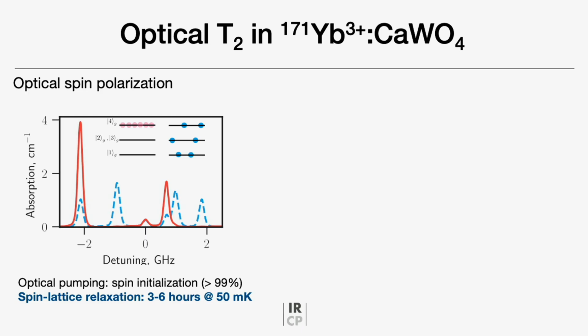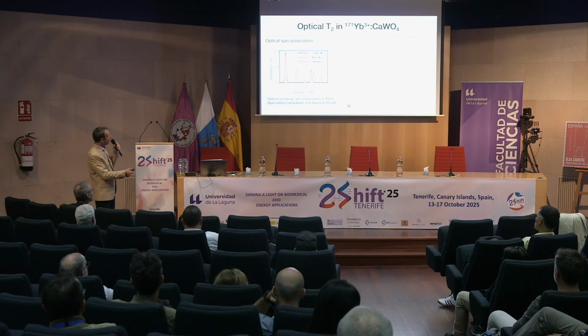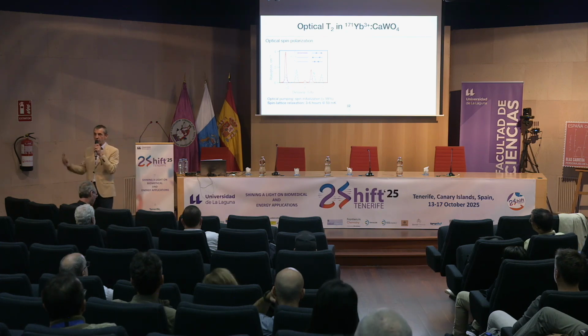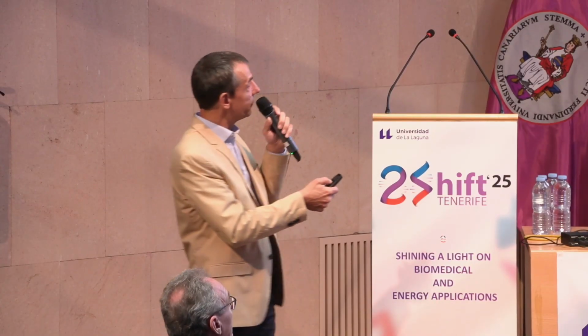So this is what we could achieve in this ytterbium doped sample. So we start from this spectrum in blue here, which corresponds to the situation where the 3 ground state spin levels are equally populated. But if we apply laser at the right frequencies on the right transition, we can end up with this situation here where all spins are now in this level that we call 4G. And so starting from the blue spectrum, we now see that we have the red spectrum, which is completely different, and we only have two transitions now. You see on this one, the absorption has been increased a lot simply because we have more population in the starting level of the transition.